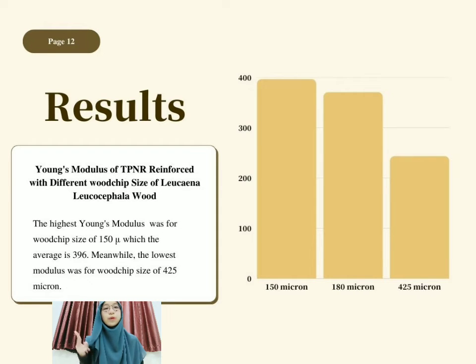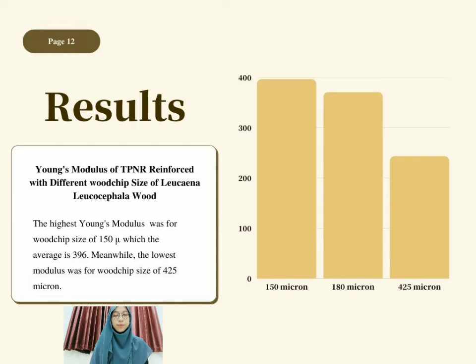Thus, for this graph, we will be able to say that if the woodchip size increases, the Young's modulus will decrease. Since the minimum requirement for the Young's modulus is between 300 to 340, only the size of 425 micrometer does not meet the minimum requirement. Therefore, for applications that need high Young's modulus, the woodchip size that can be considered is either 150 micrometer or 180 micrometer.